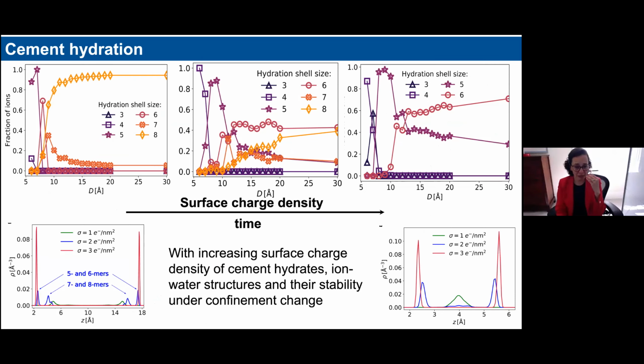These forces, this phenomenon, so the structuring of the ions, the stability of different types of ion-water structure, and the water dynamics depend on the type of ion, as I was saying, and on the degree of confinement, but they depend also on the surface charge, because depending on the surface charge, ions are more or less squeezed and more or less dense in the two layers that they form, closer or less close to the surface. So depending on the surface charge, there are different types of ion structures that you can pack. And this is important for cement hydration.